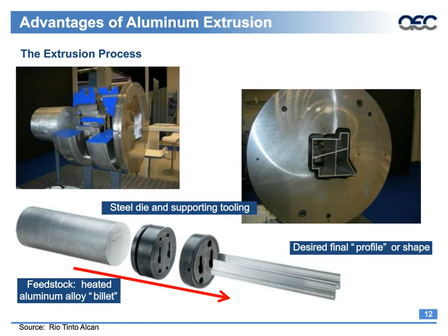So let's take a moment and talk about the extrusion process. These are a couple of different photos. Probably the easiest one to picture is the lower left, where it shows the feedstock. And that would be an aluminum log, which has then been cut into a billet size. It's heated up in a log furnace, but then it's squeezed through this die. And this particular die and backer that are shown shows a two-hole extrusion extruding out of that one-piece billet.